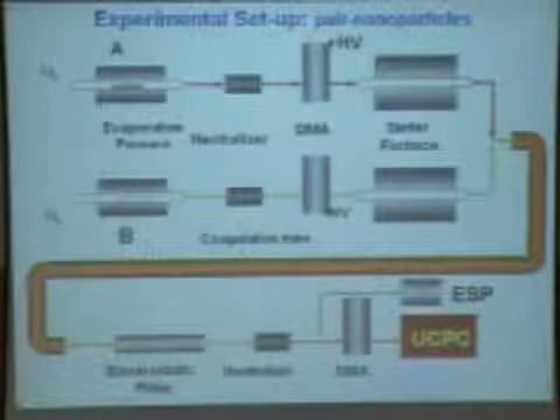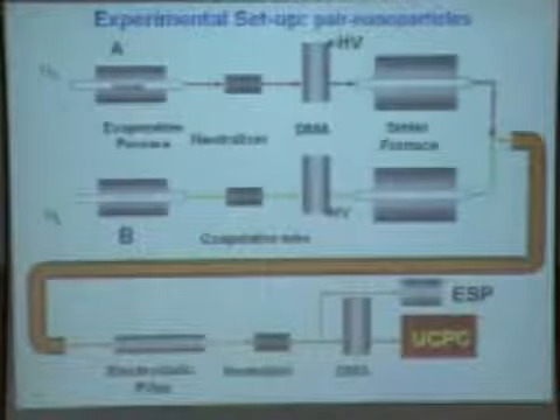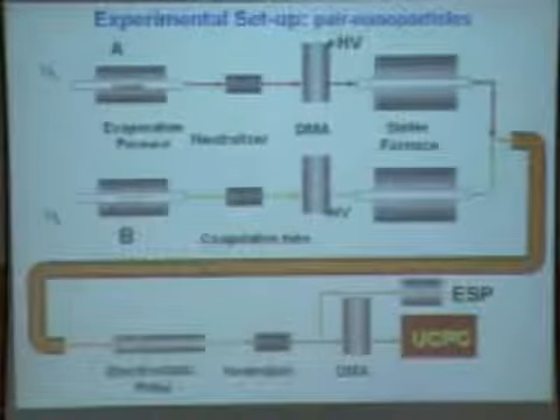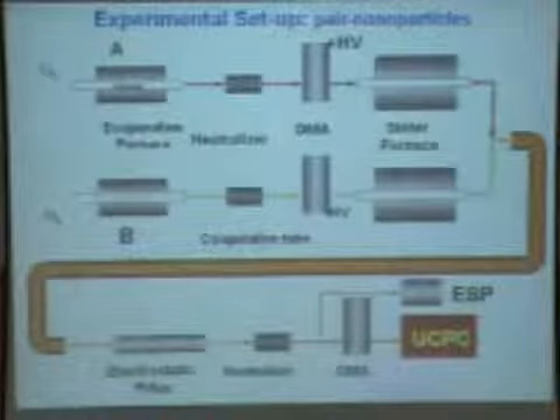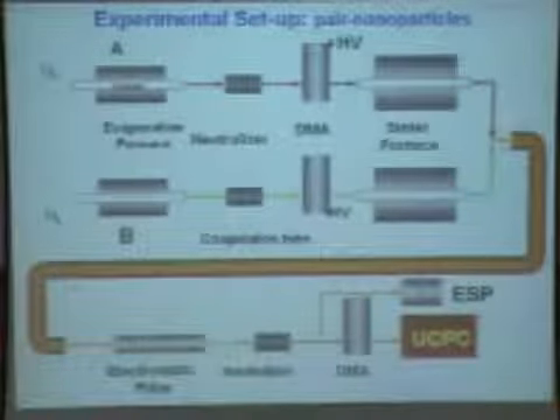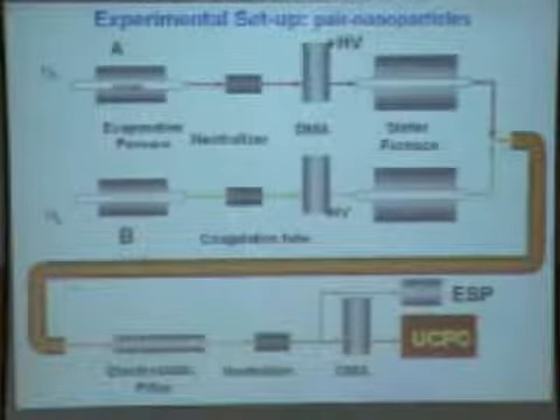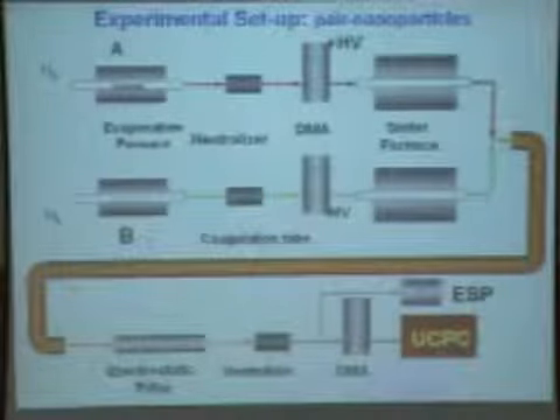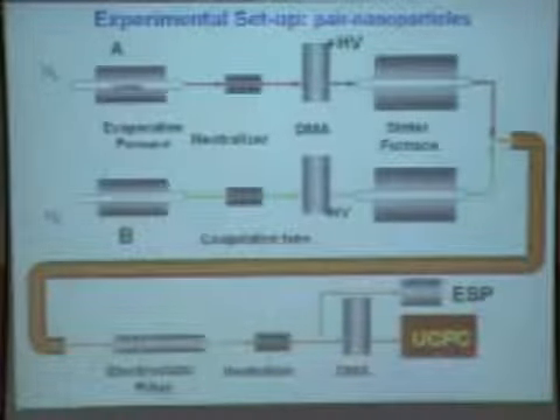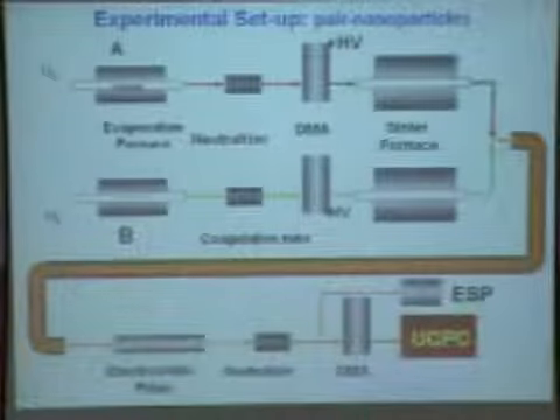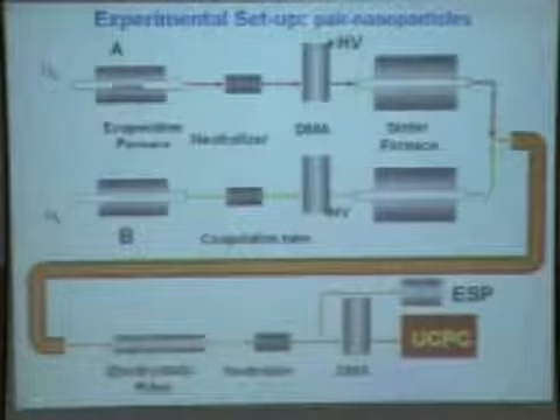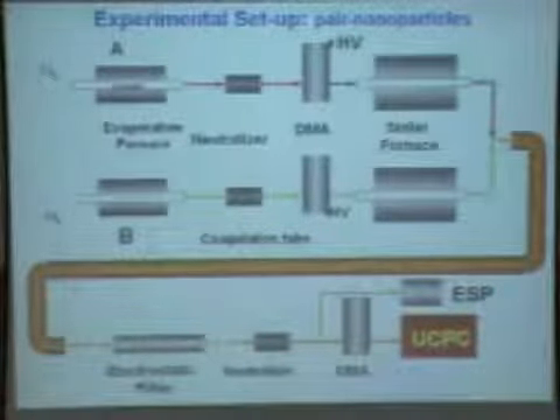And then you can also select them according to their size, because you know the size of A, you know the size of B, and you only allow the particles which have size A plus B, or mobility corresponding to A plus B, and then you deposit them. This is one of the methods by which we hope to make pair nanoparticles. And why are we interested in making pairs?